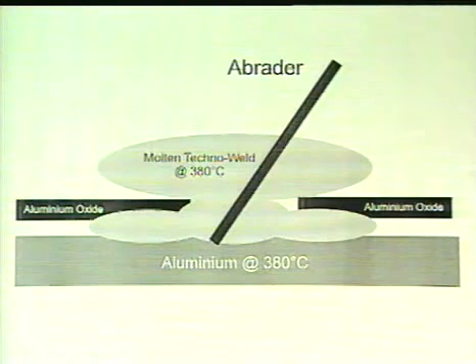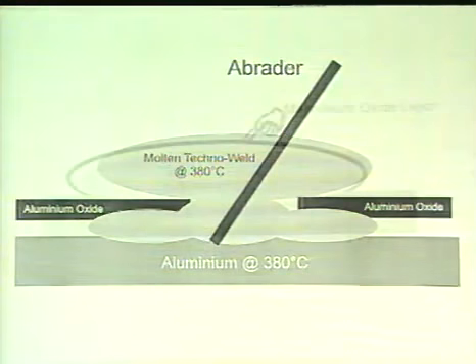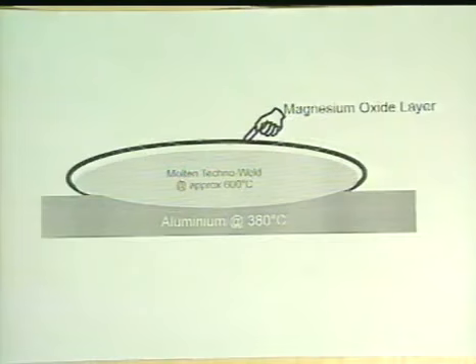Magnesium, which is also a constituent of the Technoweld rod, grabs the free oxygen to form magnesium oxide, which being very light, floats to the surface of the weld pool, preventing any further oxidization. But this reaction generates heat, which together with the background heat of 380 degrees centigrade raises the temperature in the molten area high enough to melt the aluminium, causing a fusion of Technoweld with the parent metal.